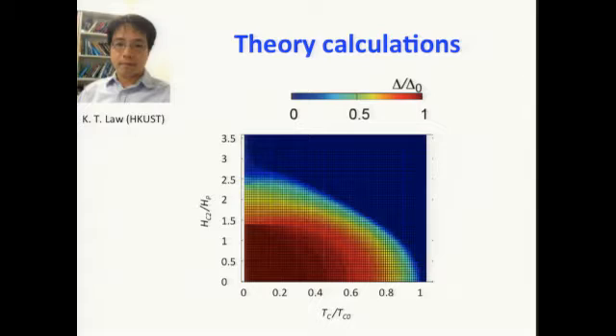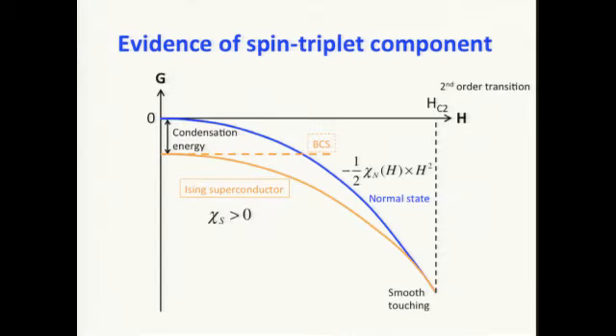Okay, so this is a theoretically calculated phase diagram, and it actually ignores the CDW order, the CDW coupling, in this case. In this calculation, do they assume that the triplet component does not change when you apply magnetic field, or is this triplet component enhanced by magnetic field? Actually it's enhanced by magnetic field. The spin susceptibility is smaller than the normal state spin susceptibility, but then it gets very close at high magnetic field, so that they can touch in a tangential way. So it gradually evolves from singlet to triplet. You can think of it as the pairing correlation where the triplet component gets more enhanced compared to singlet with increasing magnetic field.